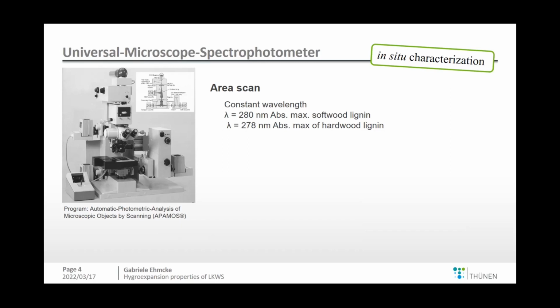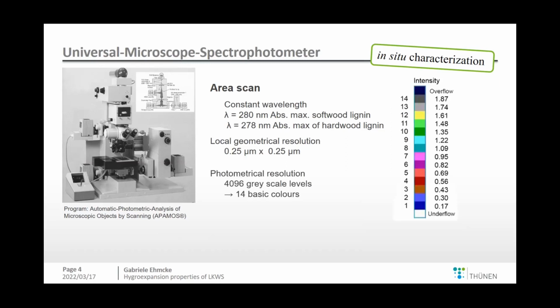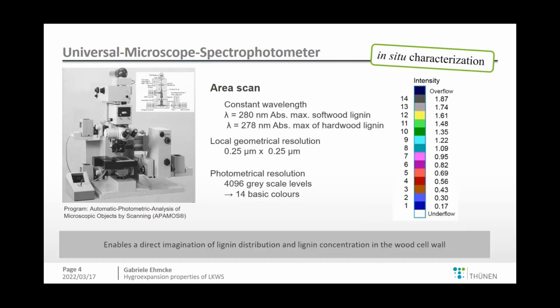If you have a softwood or hardwood, you use the maximum of absorbance for lignin. In softwood, it's about 280 nanometers, and in hardwood, it's 278. This device is able to have a very high geometrical resolution, about 0.25 micrometer by 0.25. And for the photometric resolution, we detect 4,096 grayscale levels. And these grayscales were converted into 14 basic colors, seen on the right side. So we get really nice pictures that can be depicted as 2-dimensional or 3-dimensional image profiles. And these were also statistically evaluated in a semi-quantitative lignin distribution.